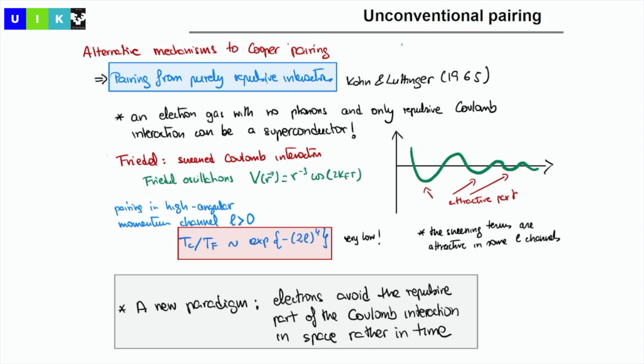So they were thinking about whether an electron-electron interaction could also become an attractive interaction and be the origin of superconductivity. In fact, what they did is they considered an electron gas without phonons and only repulsive interactions, and they showed that it can be a superconductor. And how can this be? Basically, they used the fact that when we have electrons in a solid, the Coulomb interactions are screened. And the way the screening goes as a function of distance follows the Friedel oscillations, so it has an oscillatory behavior.